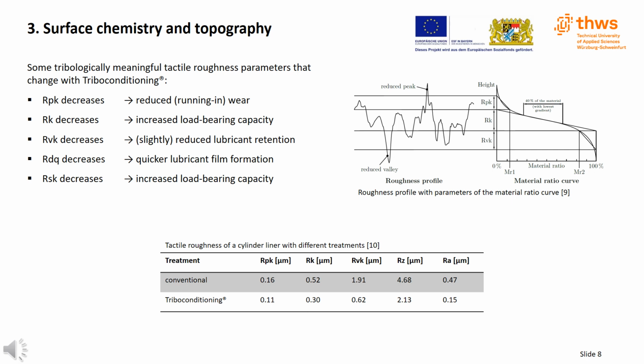Now briefly to R delta Q. This parameter describes the root mean square value of the local slopes of a profile. Triboconditioning makes surfaces smoother, so the value decreases. This leads to easier lubricant film formation. RSK is the skewness of a profile, that is, the asymmetry of the amplitude density curve. The smaller or more negative this value is, the better the load-bearing capacity of the surface. Triboconditioning leads to a reduction of this parameter.